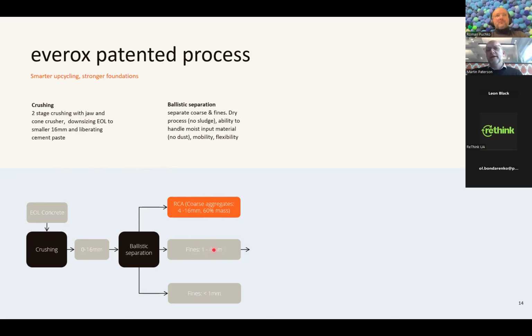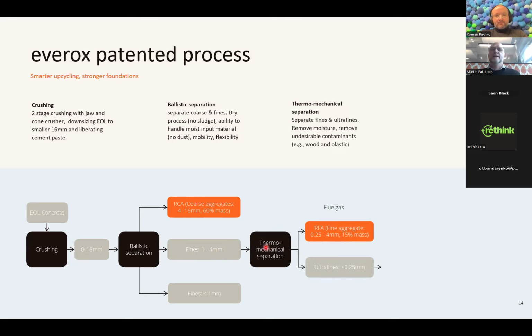The 1 to 4 millimeter fraction is actually the one which is the most difficult to clean. That's the small sand particles with still a lot of cement paste around it. Very difficult to use in construction because it has a super high water absorption if you don't clean it properly. So we put it into what we call the thermomechanical separator, our TMS. So you have the stone, you have the cement paste around it. We shock heat that bond so that at a temperature of 350 degrees, the stone expands while the cement paste shrinks, and then you crack off the cement paste from it.